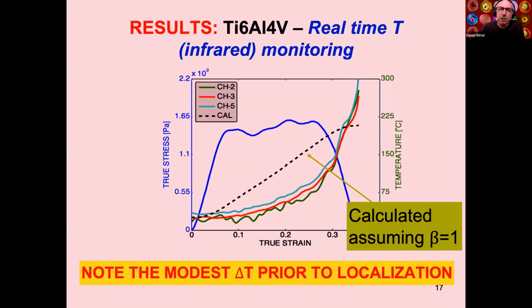And what do we see here? Well, we see something which is a little bit curious: if you believe that localization occurs here at final failure, that the shear band forms and propagates as a crack at final failure here, then you notice that the temperature rise is relatively modest. And this was reported by Marchand and Duffy, actually. Well, this was one of the inherent limitations of the detector. But if we, for a minute, forget that, they said that nothing is happening during most of the tests, and the temperature rises only at the end. This has been, in fact, forgotten or neglected, and we brought it to light again. Because if the temperature rise is negligible prior to final failure, that casts a question upon thermal softening. If there is no significant temperature rise, then where does the softening come from? That's the first question.